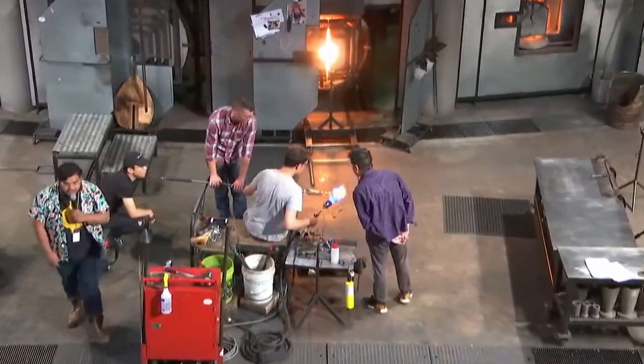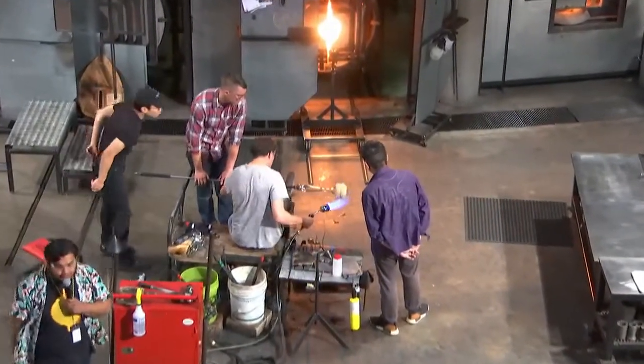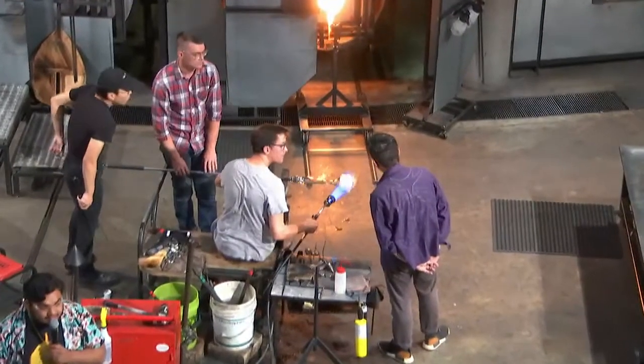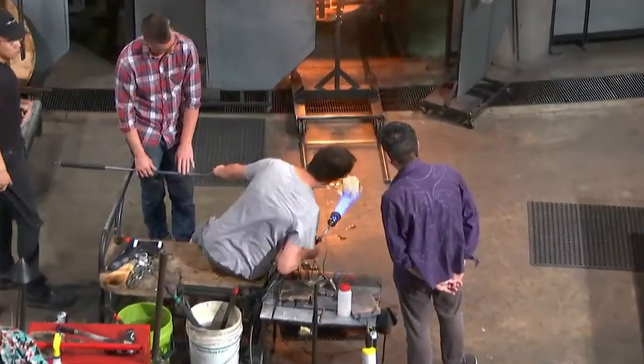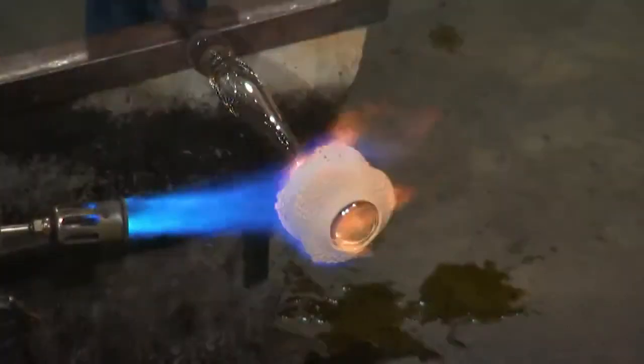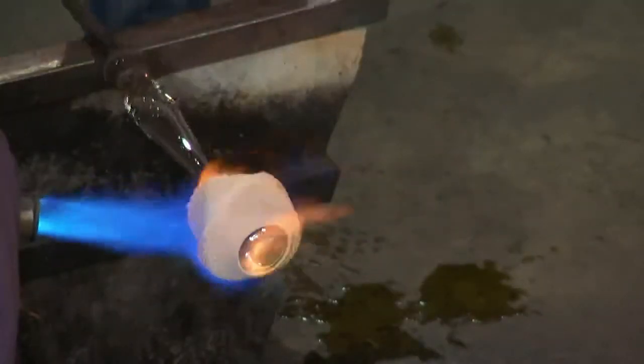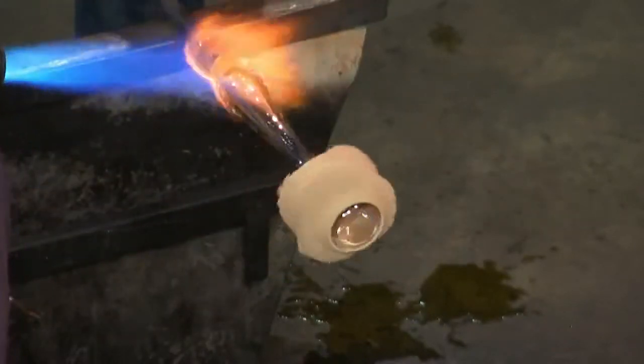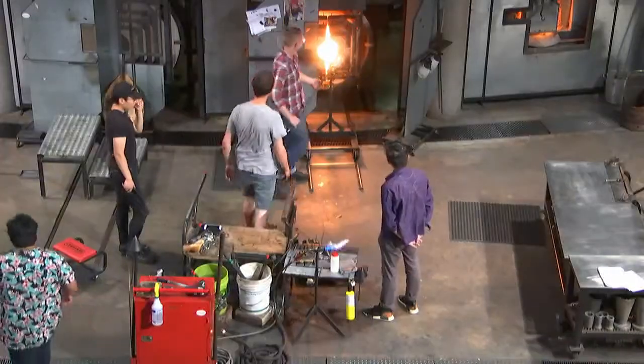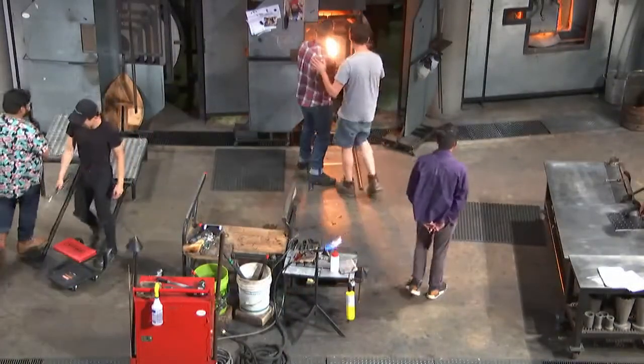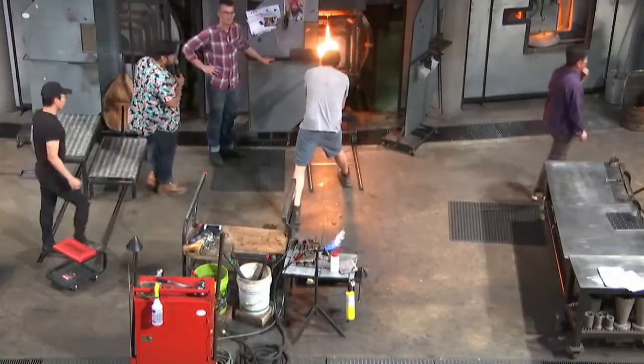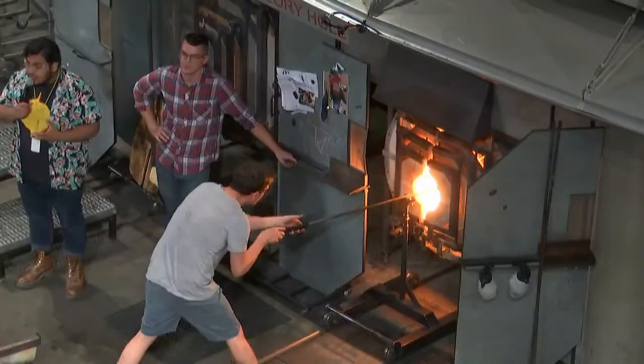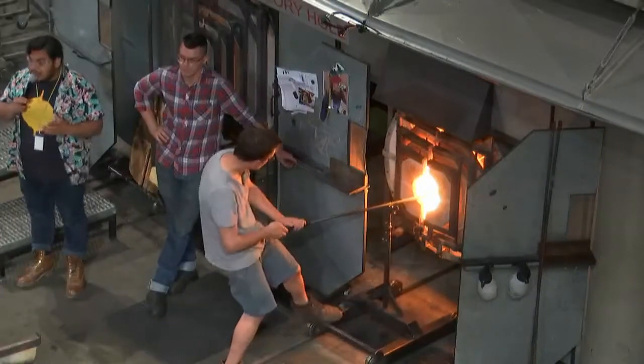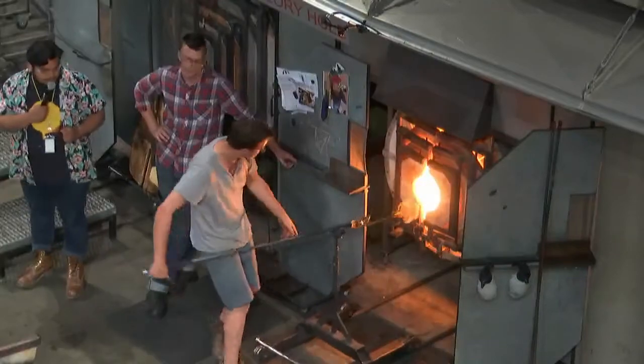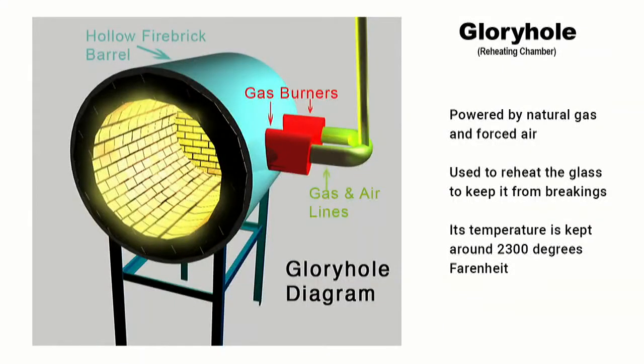One of the torches we're using here is a propane torch, approximately 2,500 degrees Fahrenheit. It's ensuring that the massive ceramic at the top is soaking a lot of heat in. Since theoretically the inside is pulling a lot of heat in, it's going to cause the glass to crack. So we're preheating to ensure it's absorbing enough energy, enough heat. We then enter the glory hole, which is about 2,300 degrees, ensuring that our whole mass of glass and ceramic is at a proper temperature so it doesn't begin to crack or break at this point. On the top screen, we're seeing a diagram of this chamber and how it works.